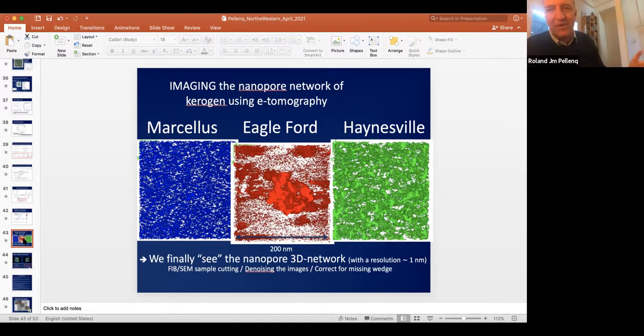So at equilibrium, the picture is very clear. CO2 will replace methane, right? By the way, once you have CO2 in the pores, you create some swelling of the carbon. As I said, maybe it can help the fracturing somehow, by creating bigger pores.